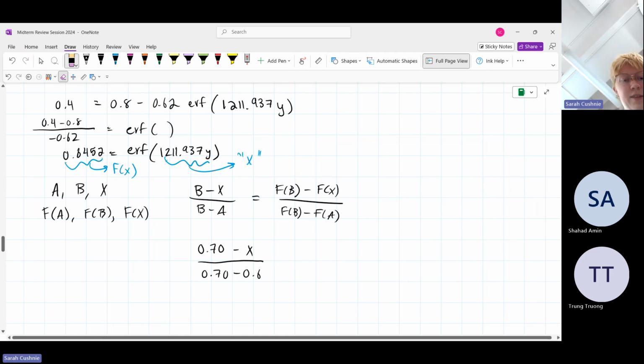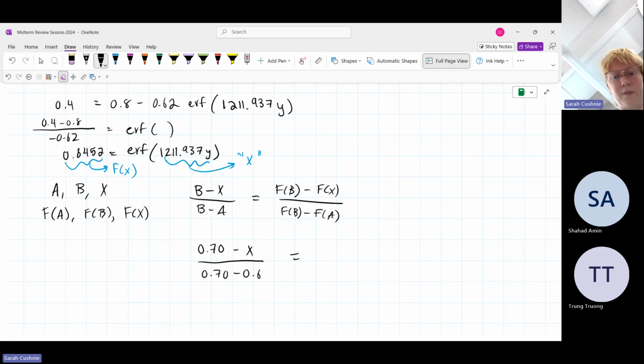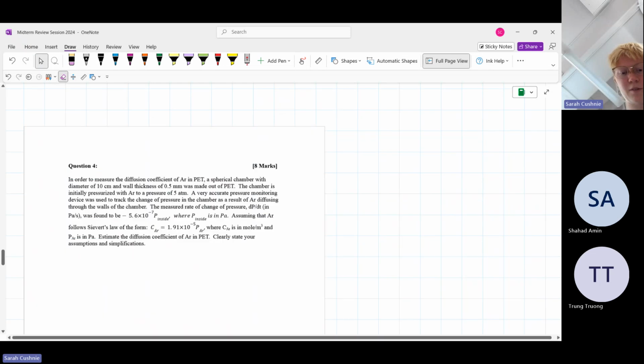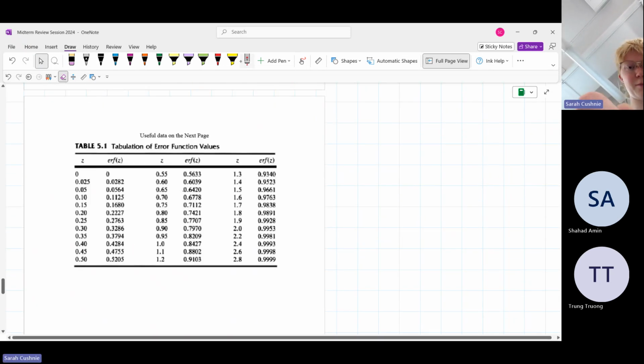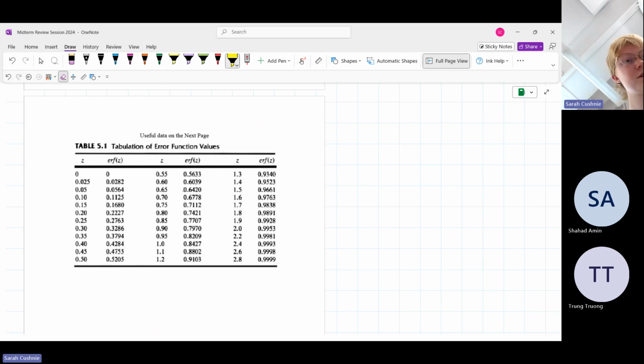So we want to have some values that surround f at x, because that's our value. Our f of x value, remember, is 0.6452. So we want to subtract it by something that's slightly bigger than it. If you look down at the table, our ERF of z was equal to 0.6452, which is going to be right in between these two values here. So we're going to take the 0.65 and the 0.7 and try to find something in between. So we're going to be linear interpolating between those two. Those are where I'm getting the numbers from.